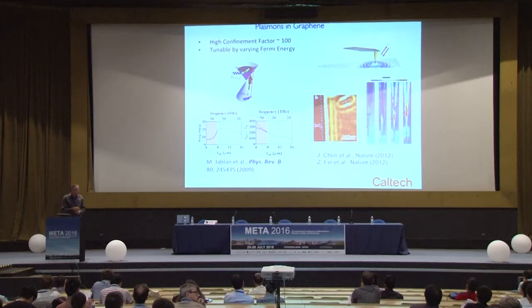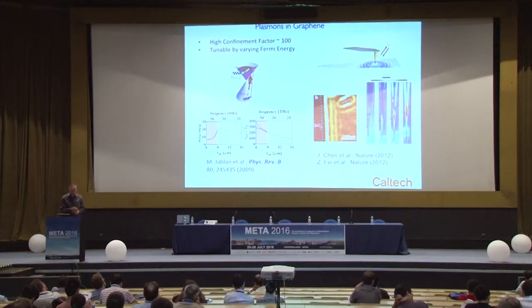And graphene, of course, has inspired a lot of attention and excitement because of the extremely high plasmon mode confinement. We see that confinement factors as large as 100 are achievable, meaning that the plasmon wavelength in graphene can be a 1/100th of the wavelength in free space. And the wave vector and wavelength are tunable by changing the carrier density, which can be electrostatically tuned, changing the Fermi level in graphene relative to its neutral condition at the Dirac point.